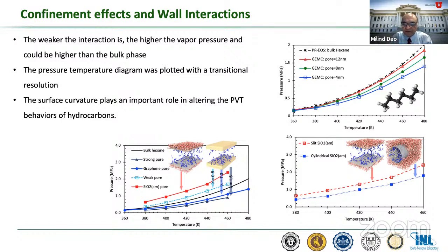This particular observation using GEMC, we have not confirmed experimentally, but molecular dynamics simulations suggest that if you have a hydrophobic surface, you're going to behave a certain way, and if you have a hydrophilic surface, it's going to behave another way. But that we have not yet confirmed experimentally. The bottom line here is that the thermodynamic behavior of fluids under confinement is affected, and the transitions are at times significantly different from those in the bulk.